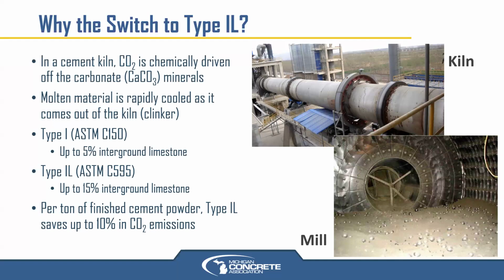Through that process, the CaCO3, calcium carbonate, you drive off CO2 in that high temperature environment, and then you're left with CaO. If you do the math on that, CaCO3 minus CO2, driven off as a gas chemically through heat, then you're left with CaO, which is lime, along with all the other ingredients that go into a cement kiln.